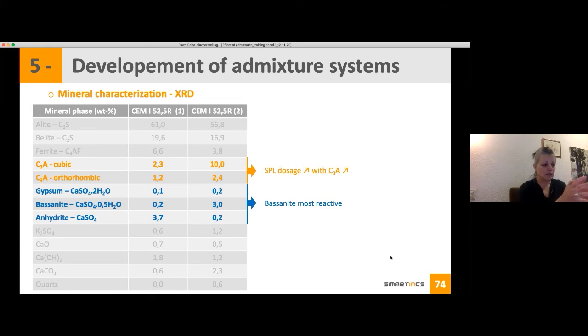Because, as I mentioned before, the first interaction that will take place between your PCE and your cement is with the C3A. It will adsorb on the surface of your C3A. So if you have more C3A, the demand and the dosage of your superplasticizer will be higher, because you will need to cover more spots than when you have less C3A. Also, one of the first reactions that will take place is between your C3A and your sulfate. Then you will form ettringite.